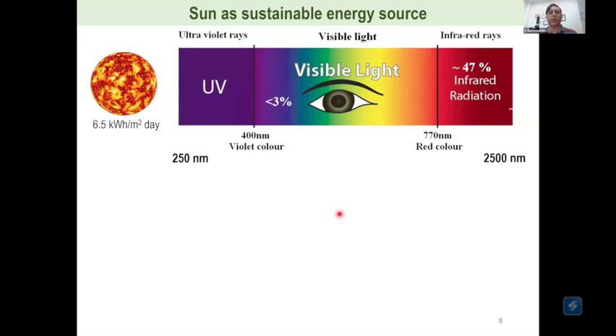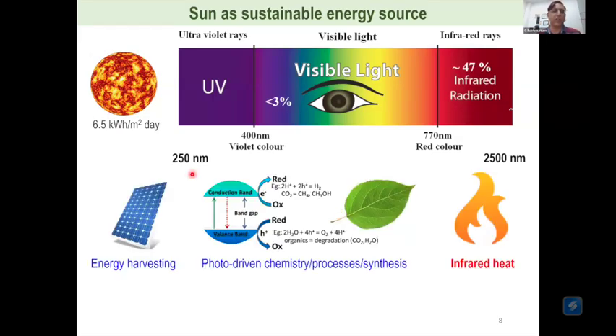So this is the problem that we started with, and said, okay, what do we do? If you look at the solar spectrum, this is basically starting from 250 nanometers, you can go all the way up to 2500 nanometers. This is the entire spectrum of light that the sun throws at Earth. And if you look at solar panels or any kind of photo-driven process, they try to utilize part of the ultraviolet region and a large part of the visible region. Thereby, they actually do have preventive mechanisms in place to avoid the infrared radiation, which contributes heat. That is the first thing that you notice, especially in a country like India. You step out in the sun, you see that it's extremely hot. So the infrared radiation is actually never a part of these technologies, which was very surprising to us.